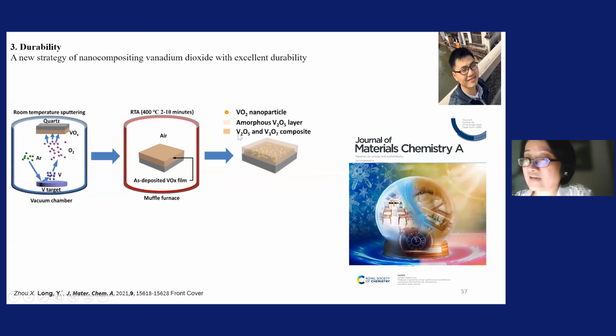these films have very good thermochromic property, number one. At the same time, the service life can be even more than 20, I can't remember the exact value now, should be more than 20 years. But for normal VO2, if you put it outside for 1 day or 2 days, it's going to fade already. Just 1 day or 2 days. So you can imagine how unstable this material is.